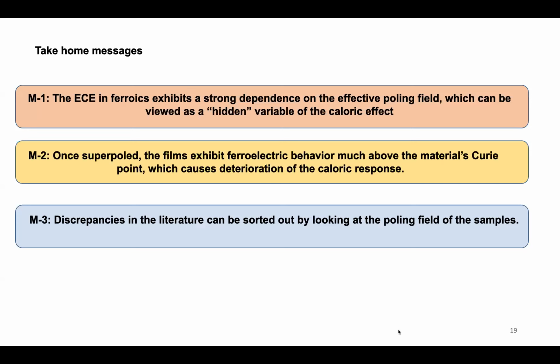So the first message is that the electrocaloric effects in ferroics show a very strong dependence on the poling field. So that can be accessed as a hidden variable in ferroic systems. And the second one is that superpoled samples may suppress the change in the temperature, I mean, it suppresses the caloric effect. And the discrepancies in the literature of these caloric studies can be analyzed using the poling field.